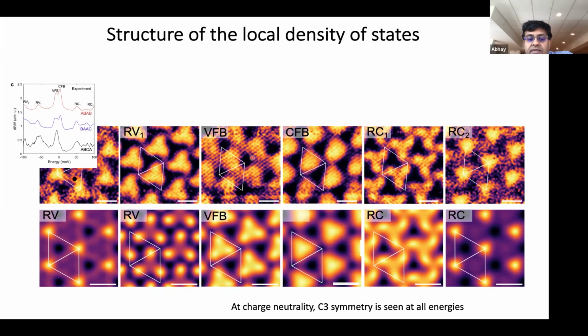And the top is experiment, the bottom is single particle theory. And you'll see, for example, these really nice, beautiful looking flower-like patterns. And why this is very important for us is that any amount of breaking of rotational symmetry becomes very obvious with these sorts of wave functions. So if you just have a dot, then it's difficult to tell if the dot is slightly elongated or not. But as soon as you have structures like this, which extend over the entire Moiré unit cell, you can easily tell if threefold rotational symmetry is broken.